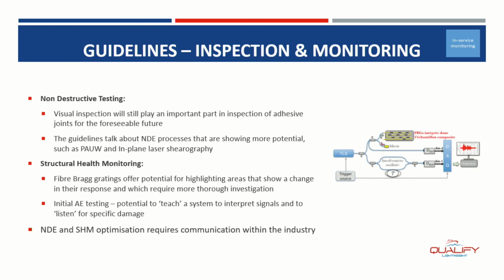As those techniques improve, the guidelines are set out in a way that they'll move with that improvement in technology, meaning that as we can see smaller and smaller defect size and we have more assurance in what we're actually looking for, then we can start really pushing those design stress levels, and we've got a lot more confidence in what the joint's actually doing. There's a lot of work ongoing on this still, and we're going to be updating the guidelines as these new techniques occur.